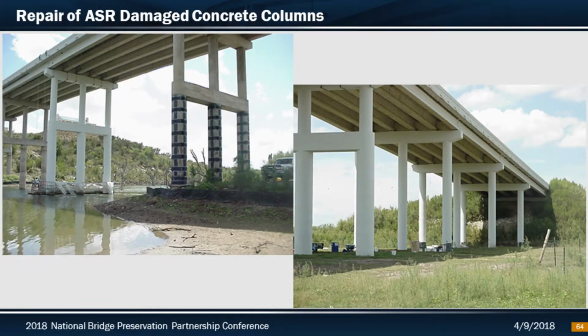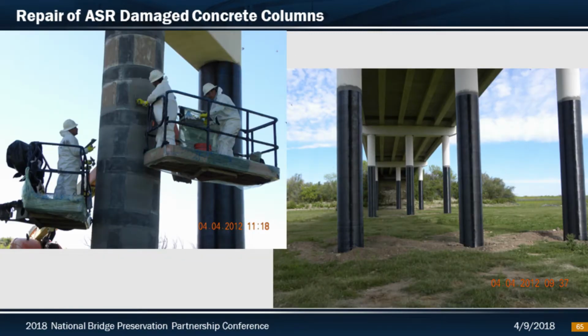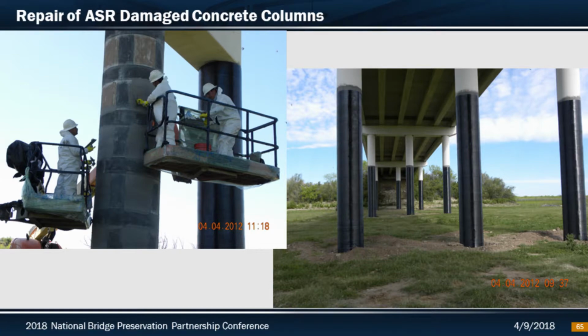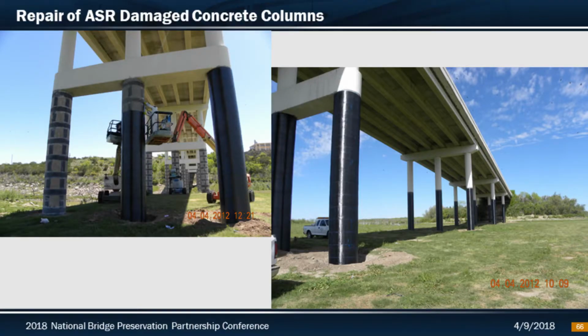Top coat was applied, and it continued to be monitored. Again, that was '04, so in '05 it was looked at, in '07 it was looked at, in '09 things appeared to be doing well, but a year or 2 later it was determined we weren't really getting what we wanted, so in 2012 we led another project to go back out and completely wrap these columns. We left the original checkerboard pattern in place because of difficulty in removal, and just did a full wrap around each column to do additional confinement. As of this time, recent inspection shows it seems that we've mitigated the swelling potential of the ASR and extended the service life of this structure. So we're 15 years in on what would have been an early age problem on a 10-year bridge structure.